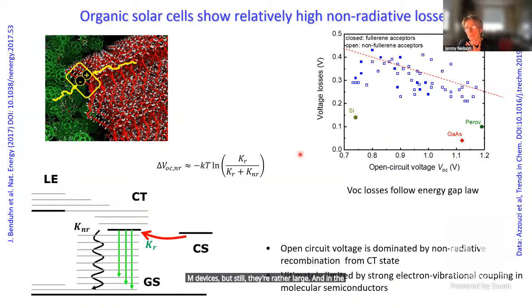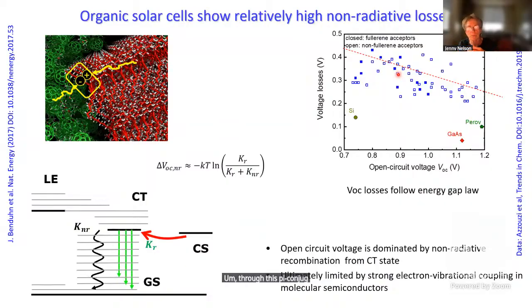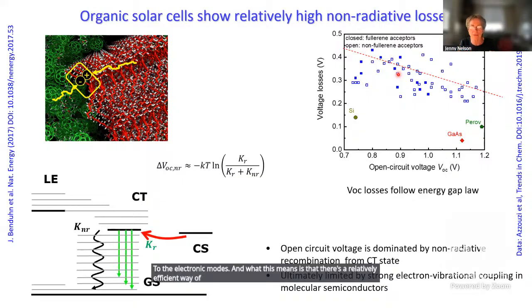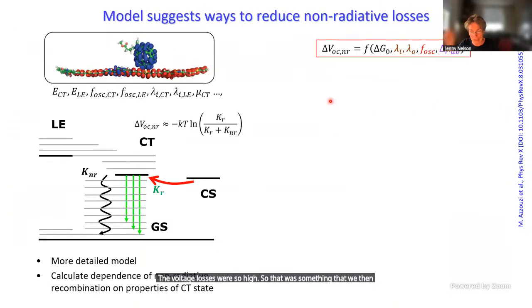In the work where this was introduced, which is a paper I've cited over here, the argument for why these voltage losses were high was all to do with the chemical structure of the materials. The materials are made from carbon atoms linked together through this pi conjugated backbone. The vibrational modes of these carbon-carbon networks are quite high, and they're quite strongly coupled to the electronic modes. What this means is that there's a relatively efficient way of dissipating energy, of losing energy, for the first excited state to decay to ground. It was proposed that that was the reason why the voltage losses were so high. So that was something that we then explored in my research group.